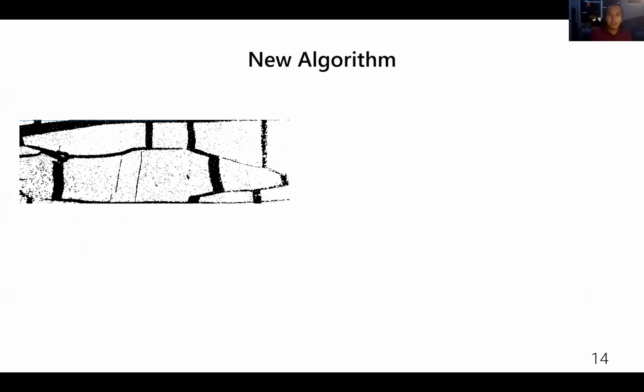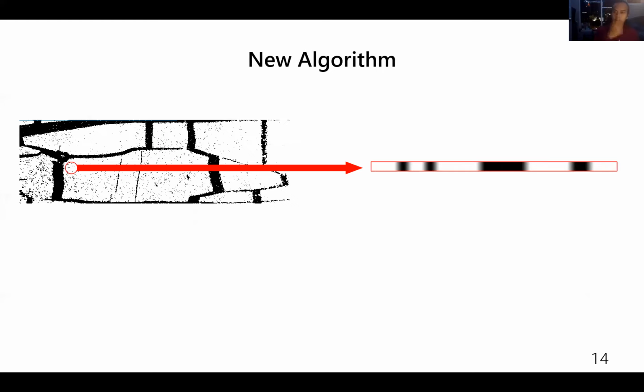So to give a little example case, if we take a small portion of an image, the first thing the program would do is measure all the widths and the gaps in the image, as you see here. We'll then take into account the minimum gap width entered by the user, which is 5. So the program would automatically look at this and see here that there is a 5. This acts as a breakpoint. So it just gets rid of this defect and does not think about it anymore. And it then goes to each remaining section. In each section, it adds up each of the ribbon widths, as well as each of the gap widths.